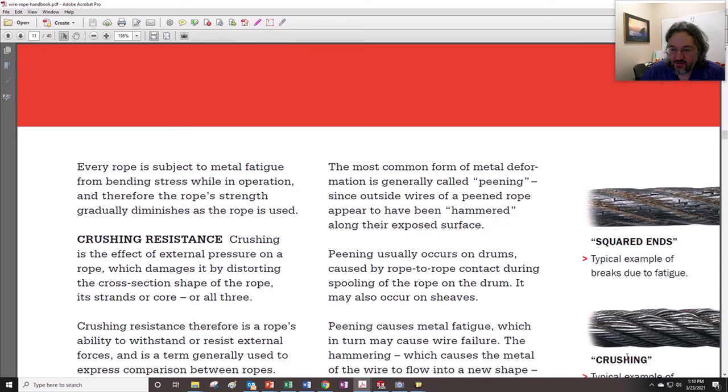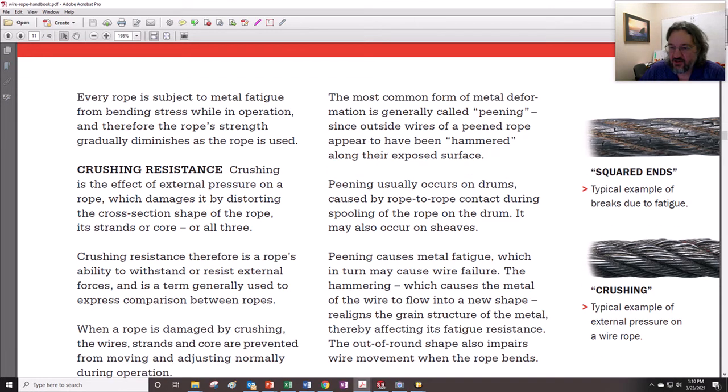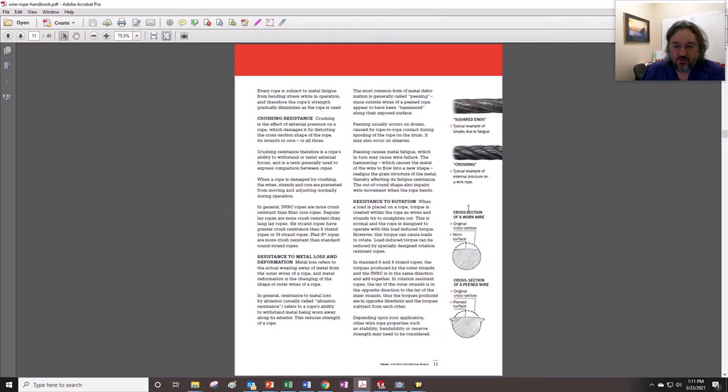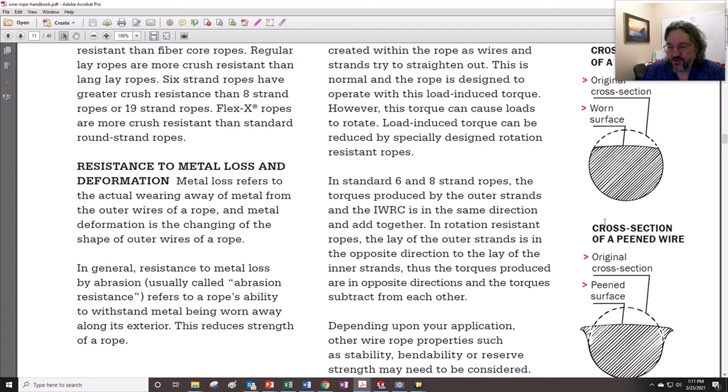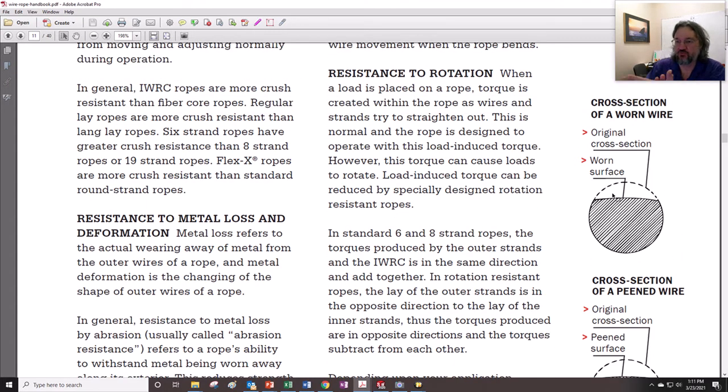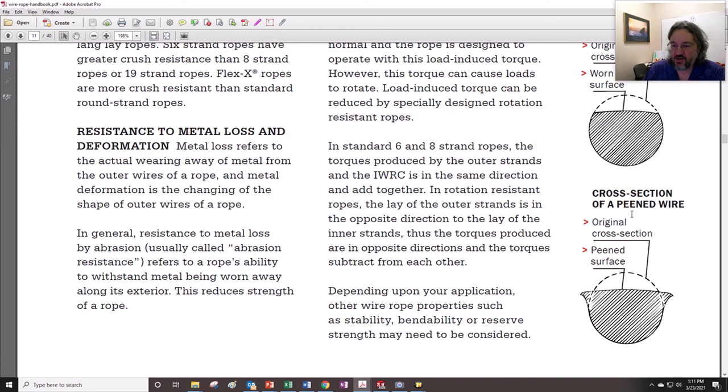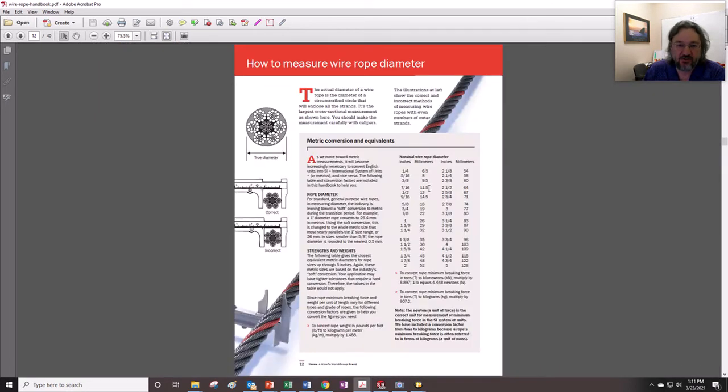Some of the ways that things fail, like, so right here's a couple of good things here. You can see that this right here is basically a typical thing that happens when you have fatigue, right, has ended. But here we have, you can see this, that the wire can be crushed, right. And that could be because of being on the drum or it could be because it was going over a sheave or going over just like a rail or something, but also the wires can be crushing each other when if you're going to have multi-layer wraps on a drum. So those are failures to look out for. It's interesting here that you could see the cross section of a worn wire where it's been rubbed onto something here, but you could have something where it's a cross section of a peened wire and that's almost something that's been hitting on top of it instead of, so you have rubbing, but we also have like kind of like a more of a crushing type of failure that you could see in individual cross sections.